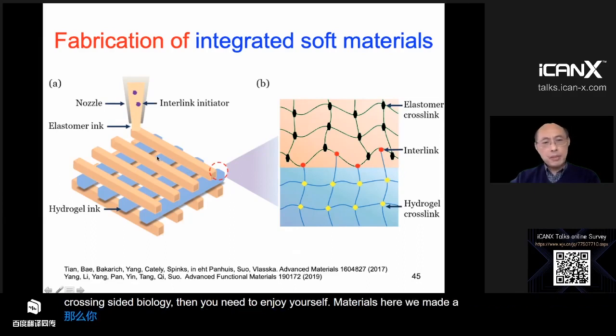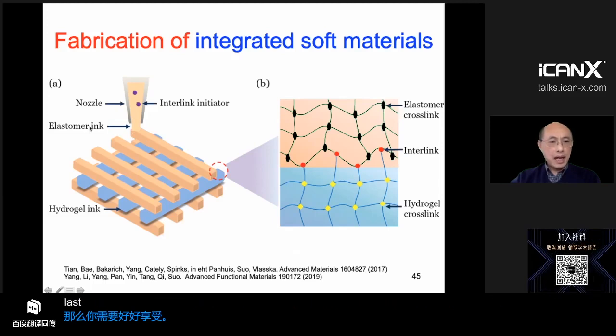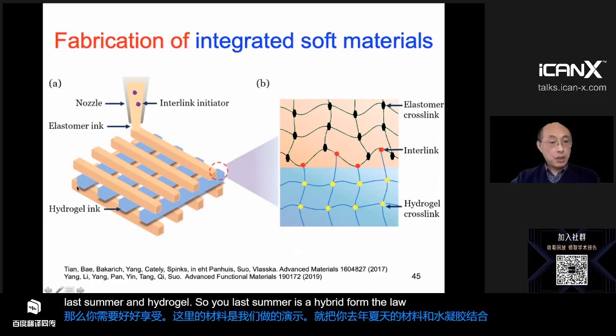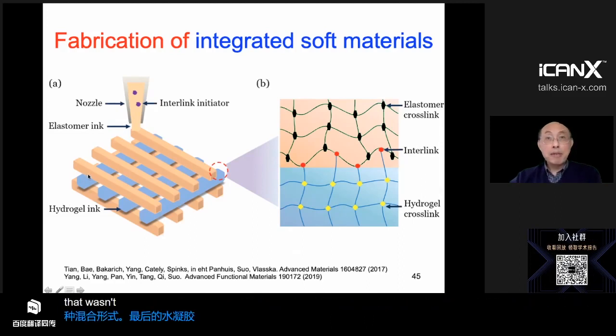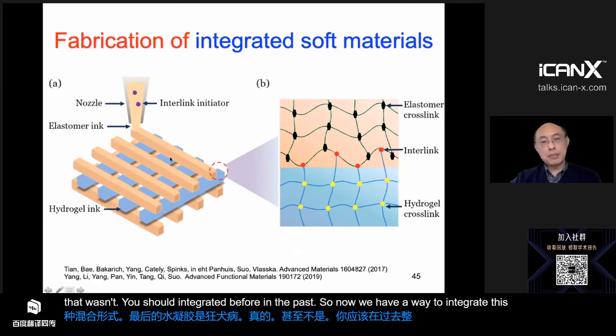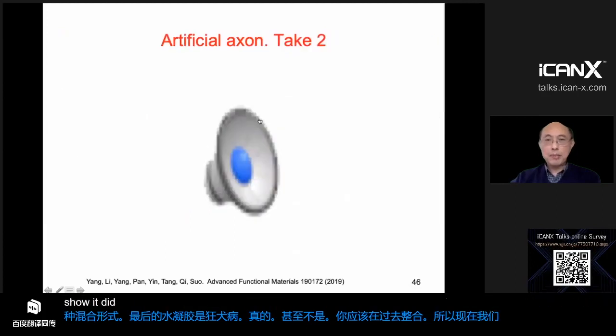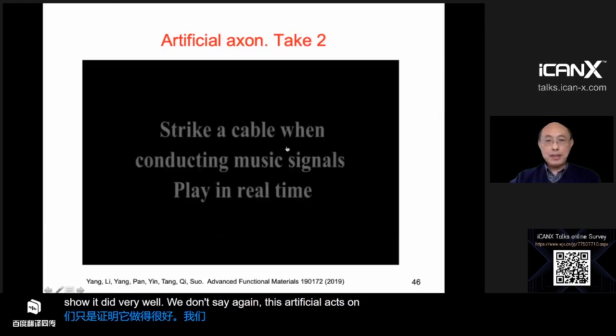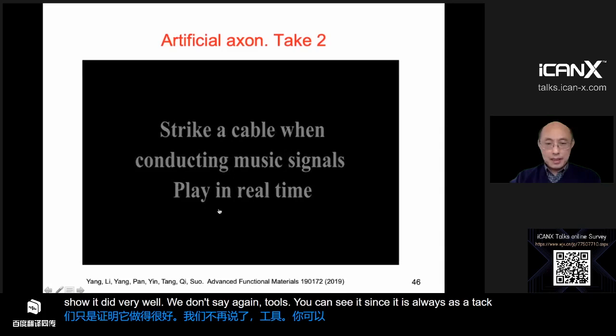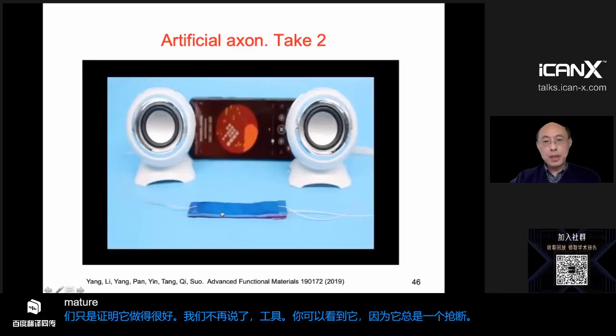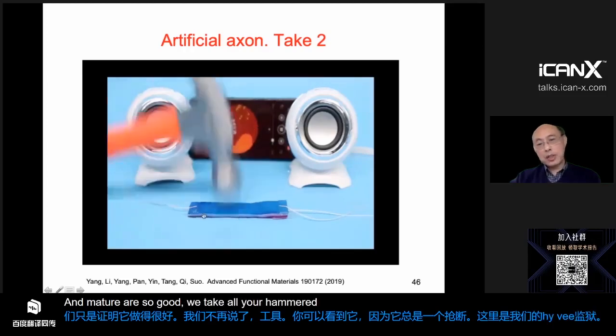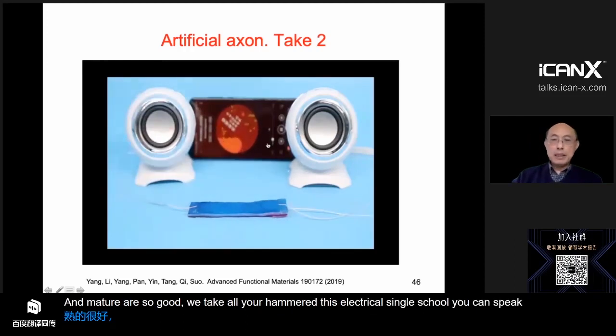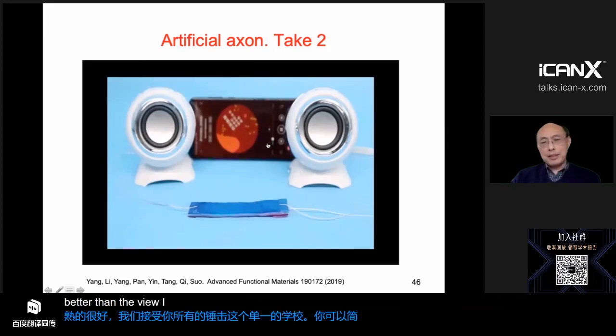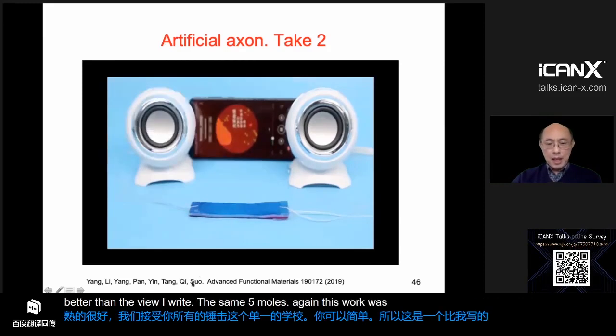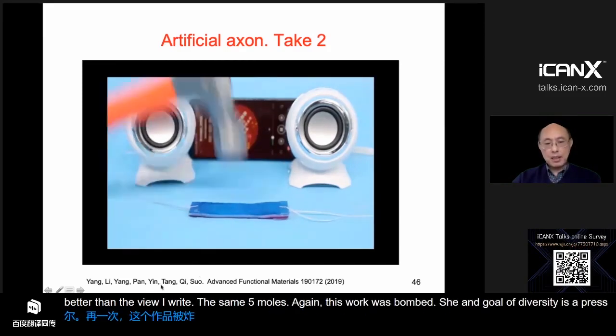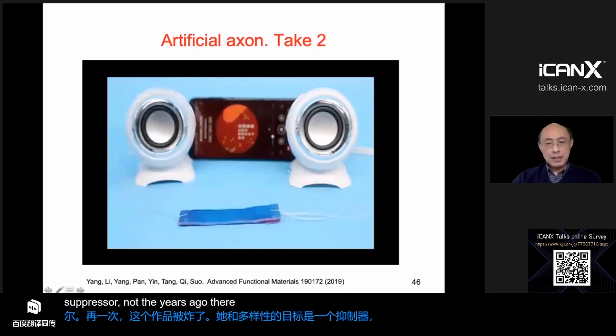Here we made a preliminary demo, just integrating elastomer and hydrogel. Elastomer is hydrophobic. Hydrogel is hydrophilic. Even that wasn't integrated in the past. So now we have a way to integrate this material, and we show it did very well. We demonstrate again this artificial axon. You can see the result is just spectacular. Here is our hydrogel, and its material is so good we can use a hammer. While you hammer, the electrical signal goes through, you can still play with it. So this is better than a real axon, right? It can sustain high load. Again, this work was done at Xi'an Jiaotong University with Professor Jingda Tang. He is a young faculty, very creative, a new star in the field.